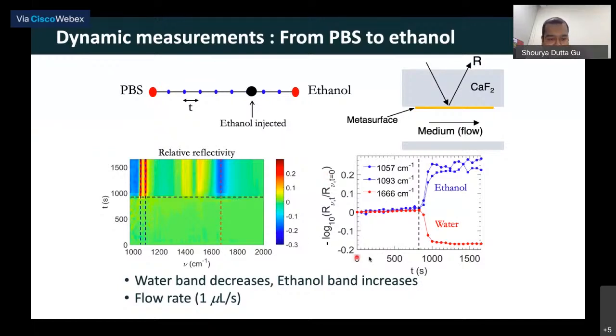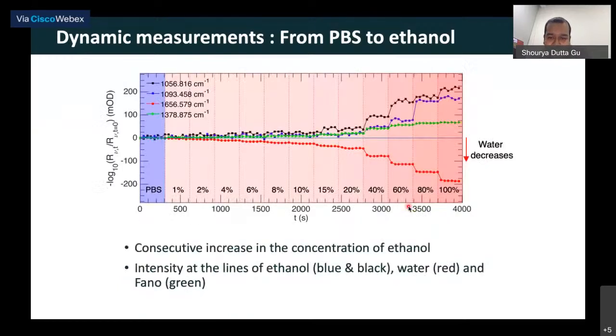Now, if you plot as a function of time at one of these bands, we see that the signature of water reduces and the signature of ethanol increases. So you can do dynamic measurements using this system, right? Then if you are just interested in sensing, you can make a calibration chart. You do a series of concentrations, starting from pure PBS or a mixture of PBS and ethanol at different values, and you see that the signal changes progressively. By making a calibration curve, you can say how much ethanol is there in the solution, right? Now let us apply this system to human cells and see how we can apply it for diagnostic purposes.